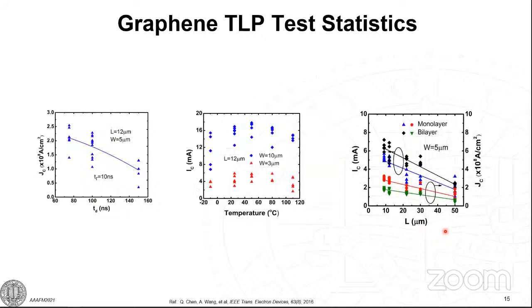And more interestingly, we actually show the temperature behavior. When you do the thermal annealing, you actually see a bell-shaped curve. So that sort of means you can optimize the design through manufacturing technique. We also show the monolayer and the bilayer. Basically, it shows a bilayer can conduct more current compared to the monolayer.